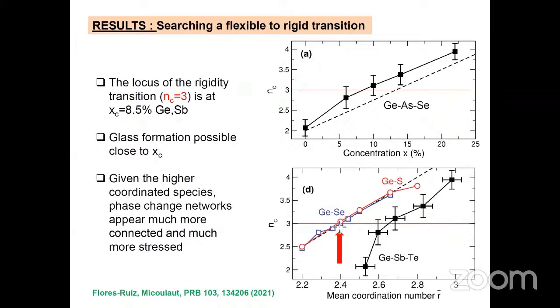If we compare now those numbers with, let's say, archetypal selenides, which have been investigated in the context of rigidity transitions, we see that the shift of this isostatic criterion, which is at 2.4 in these typical binaries, is shifted to higher coordination numbers. And this arises from a mixed effect arising both from an increased coordination number of the species, but also a reduced fraction of topological constraints, because some of those constraints are broken. We have also a reduced fraction of tetrahedra in the systems as compared to GeSe or GeS, where the fraction of germanium tetrahedra is 100%.